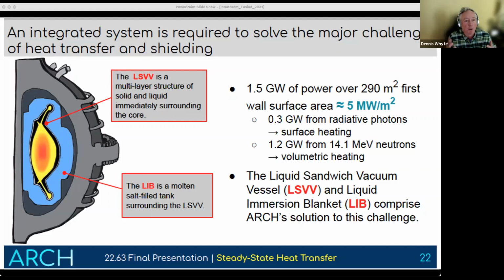If you can keep the salt pure, the nuclear physics of this involves only low atomic number things: fluorine, lithium, beryllium. They make temporarily activated components, but with such short half-lives that it's basically non-radioactive after a day or two. That's an immense advantage, a safety feature of fusion. But if it's got even small amounts of impurities, like flakes of metals, those will dominate its radiological profile rather than the salt itself. So those are the two reasons we would keep it pure.